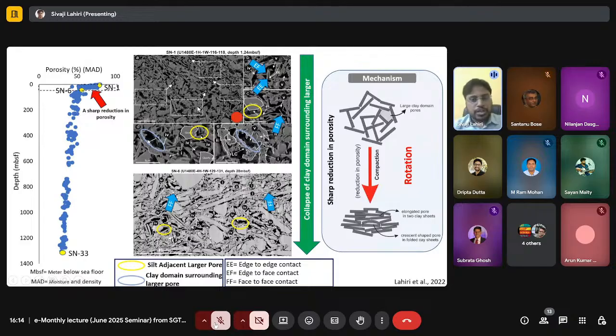Now coming to the deformation mechanism, in the sample SN1, we dominantly observe 3 different types of particle contacts, that is edge to face, edge to edge, as well as face to face particle contacts. However, in the sample SN6, we dominantly observe this kind of face to face particle contacts. Now based on this observation, we can conclude rotation appears to be the dominant deformation mechanism at the shallow depth from seafloor to 30 meter depth.